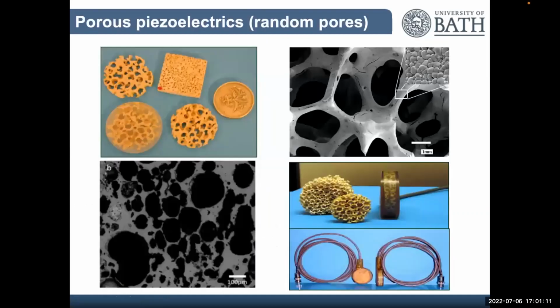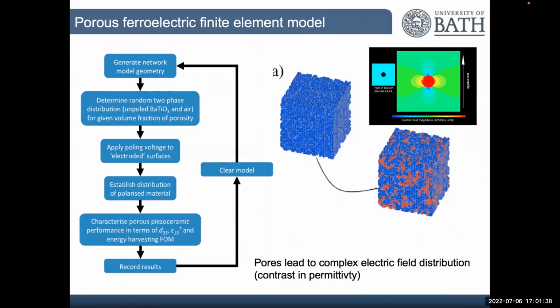I've worked a lot on porous materials over the years. Benedict mentioned I used to work for the Defence Evaluation and Research Agency. So we were using those to make hydrophone materials. Large voltage means that we can use them as high sensitivity sensors. And by introducing porosity, what we're doing is reducing the permittivity of the material. So we're driving those figures of merit up. We have some very nice models at Bath now where we can model the poling process within these materials. Remember, we need to apply a field to align those dipoles to get a macroscopic alignment.